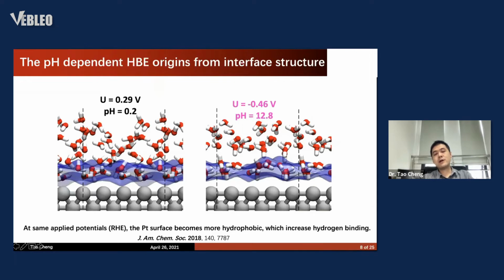If we look very closely at the interface, we can see it is actually different. Basically, at high pH, the distance between the first layer of water and the electrode is a little bit further than in the low pH case. In this case, it means that the water has weaker interaction with the metal, which in turn means stronger interaction with hydrogen. So now we can not only capture the trend, but also explain the hydrogen binding energy trend on the pH by looking at the microstructures. What we propose here is that when the pH is higher, the surface is actually more hydrophobic.